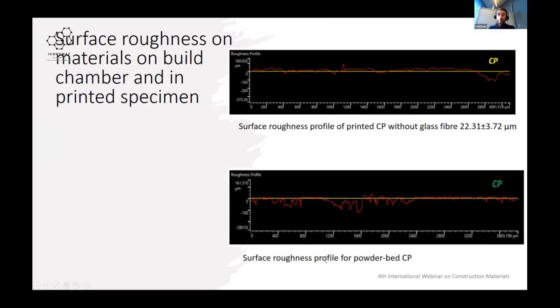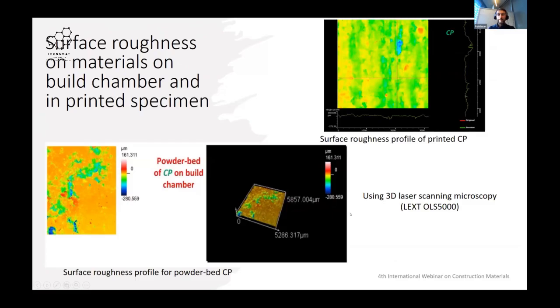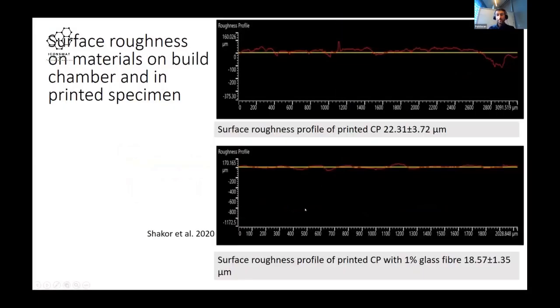We also checked the profile of the cementitious material in the powder bed chamber. It is a very high surface and non-homogeneous as well. This can be seen in 3D, which is just an extra explanation. But once we added 1% of this glass fiber, the roughness changed from 22.31 microns to 18.57. So it means the glass fiber improves the material's homogeneity and surface roughness by about 20%. You can see here that the surface is quite good compared to the material that does not include the glass fiber.